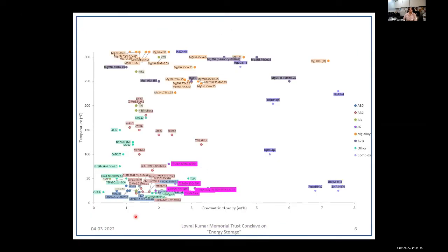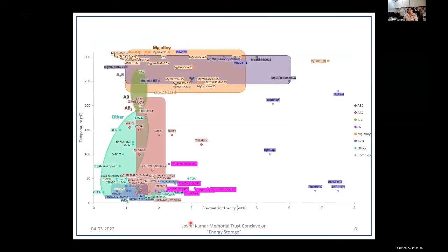Now, if we quickly see, at 1 bar pressure, as a function of absorption temperature, the storage capacity of such metal hydrides, if we try to put them together, then we can see that there are different regions of different metal hydrides. There are regions wherein the metal hydrides have a very high gravimetric capacity, but at the same time a broad window of operational temperatures, which can be even very high, beyond even 200 degrees centigrade. There are very high capacity materials like magnesium and magnesium based alloys.